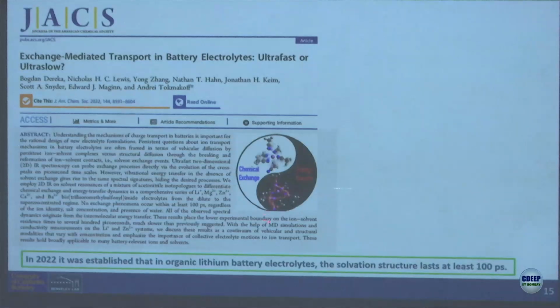You can see, for example, they say that ultra-fast 2D IR can probe exchanges. However, in the absence of solvent exchange, you get the same signatures, hiding the desired process. And we estimate that no exchange takes place for at least 100 picoseconds. So in the liquids that we have been carrying in our pockets, until 2022, it wasn't known if it was 1 picosecond or 100 picoseconds.